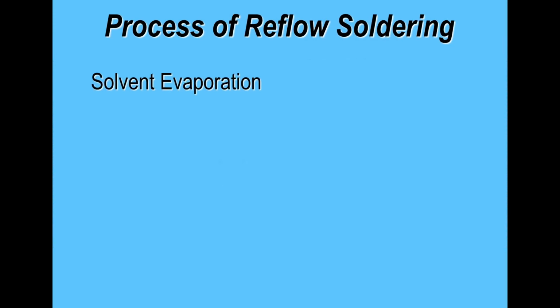So let's talk about the basic process first of all of reflow soldering. And it has changed over the years, but the fundamental process steps that you need to consider is first of all the solvent evaporation from the solder paste that we're going to be reflow soldering. And the solvent within the system may be one or maybe two different solvents to deal with the printing characteristics and also hold characteristics while the printed circuit board in a printed state is held prior to the reflow process. And this, generally speaking, is minutes rather than hours, but it just depends how you run your facility.